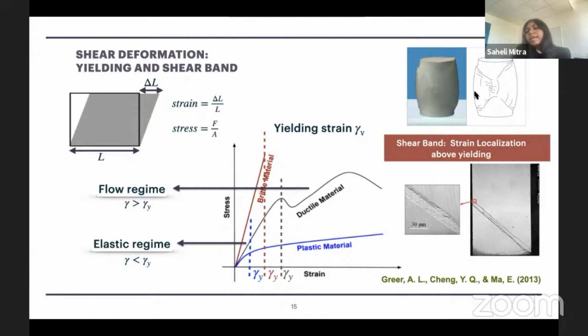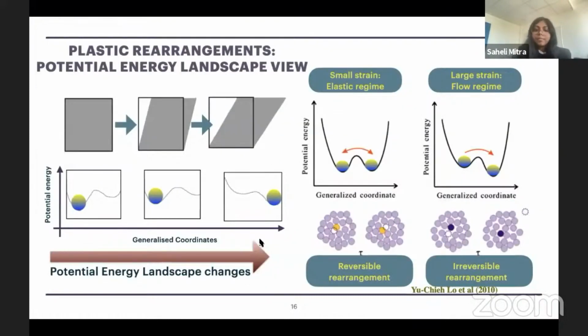On top, I have an example from a piece of mud, and below is an example of shear band formation for a metallic glass. So now the question is, for a system, how do the particles rearrange in forming the shear band? For that, let's see what happens from the energy landscape perspective. If I am shearing a system, what I am doing essentially is changing the potential energy landscape. At some point, the system prefers to sit in the local energy minimum basin.